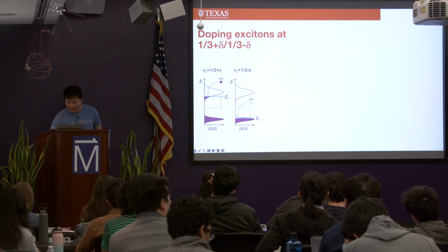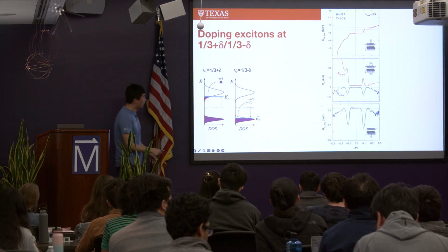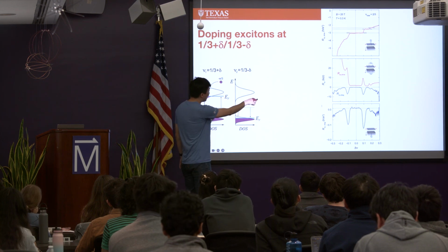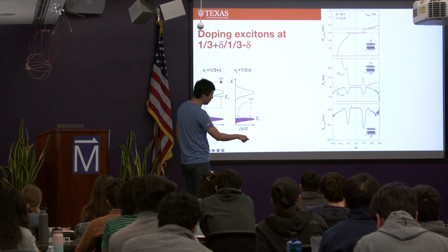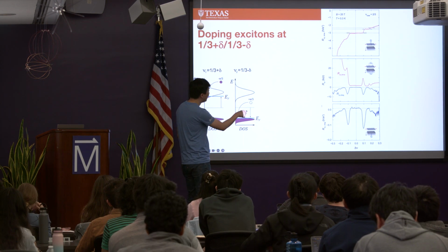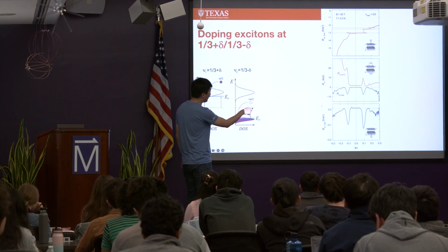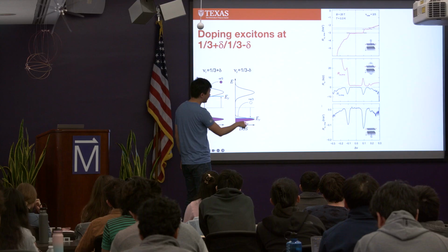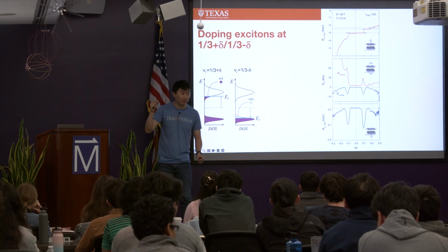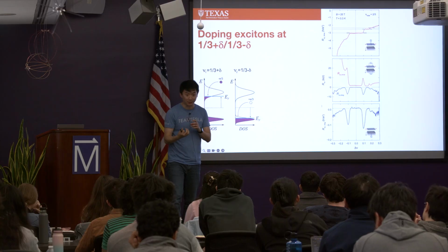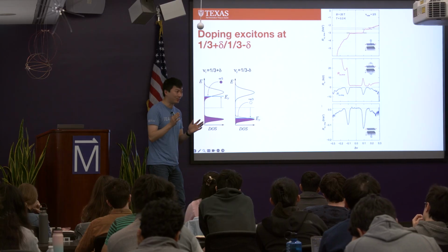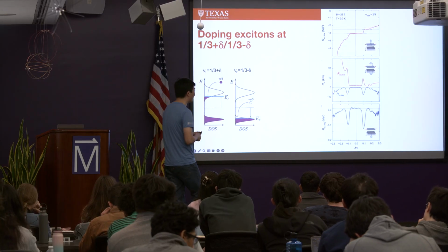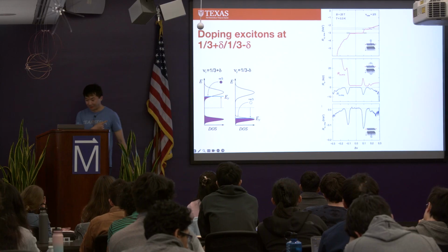And so in a Hall-bar measurement, on the drive layer, you see this 1/3 plateau. Now we're changing delta nu as the x-axis, right? When we start to imbalance the two layers, at some point, the plateau disappears. But right around the time the plateau disappeared, this is drag data. There's a very large drag response, meaning that the two layers start to show correlation, right? Right around the time that you close the charge gap. So this is the Hall-bar data.